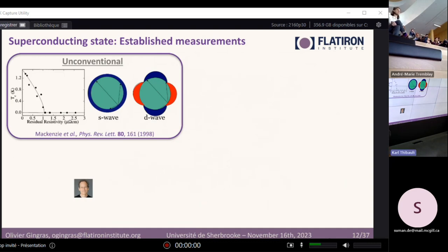We're going to put the animation here, but here are some of the established facts about strontium ruthenate. First of all, all the experimental measurements I'm going to show basically point to it being unconventional. The first experiment that highlighted this fact was that when you add non-magnetic impurities, it quickly destroys the superconducting state.